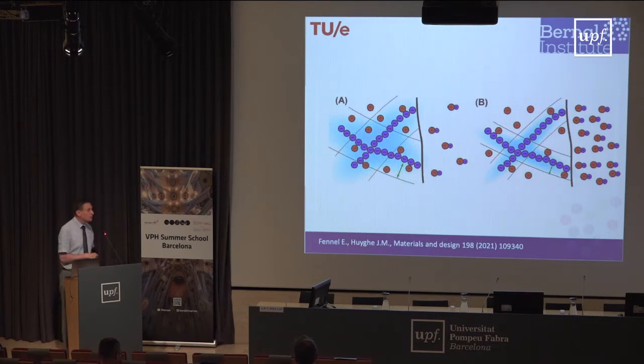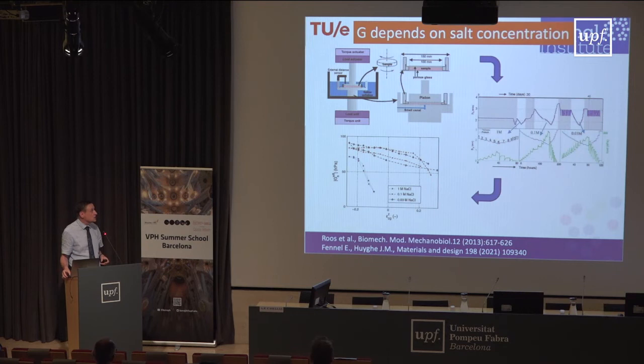Now, even if you keep the salt concentration and the deformation absolutely constant, but this time you change the outside salt concentration, then you change basically the thickness of those double layers. So this is the Debye thickness. Here in high salt concentration, here low salt concentration, it changes the thickness of the double layer. And part of the stiffness of a gel is related to the thickness of those double layers and not just to strain. Even if you constrain the gel and disallow it to swell, you get a change in stiffness.